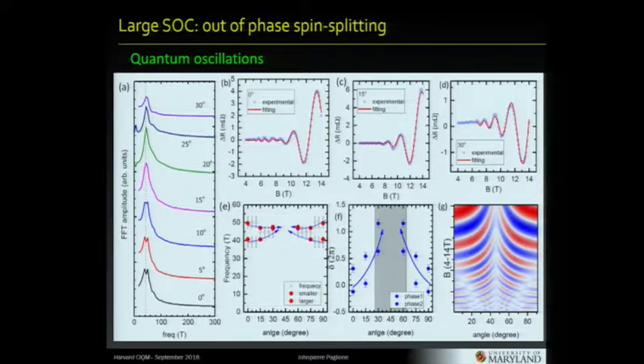And then this is a simulation of this kind of two frequency model with pi phase difference between them, showing that you exactly reproduce the experimental data that we see in the measurement. So it's quite fascinating, and it's most likely, at least this part, is old physics. It's Pippard physics from years ago, but it's never been observed. So at least we don't know of an experiment with quantum oscillations measurements where the amplitude of the quantum oscillation suddenly disappears for all magnetic fields. As far as I know, this has been seen. So it's a neat piece of physics that we pulled out of this experiment.